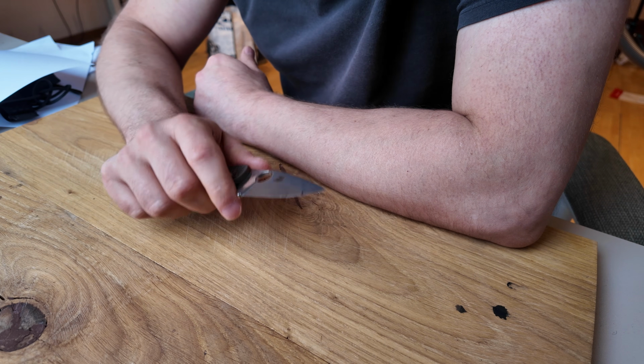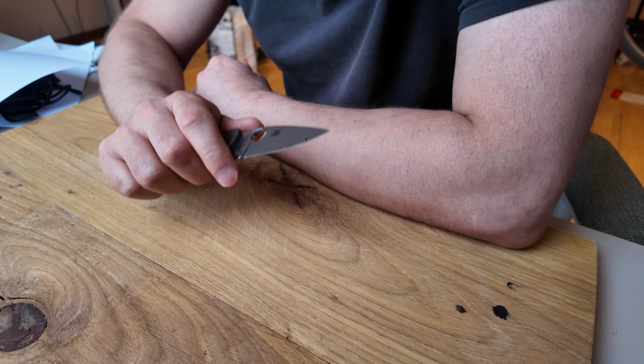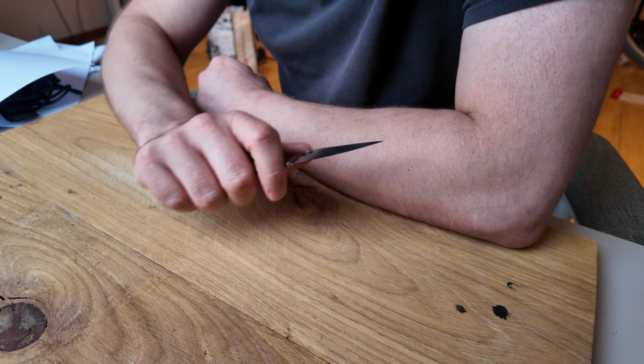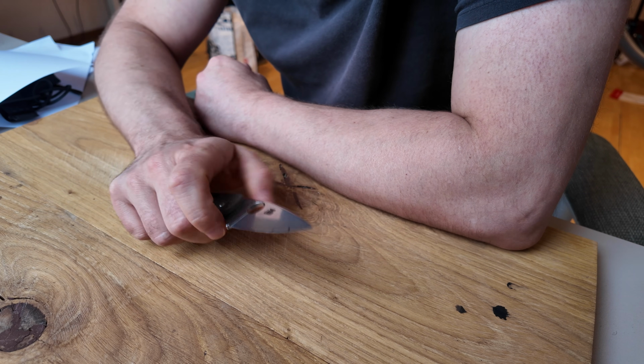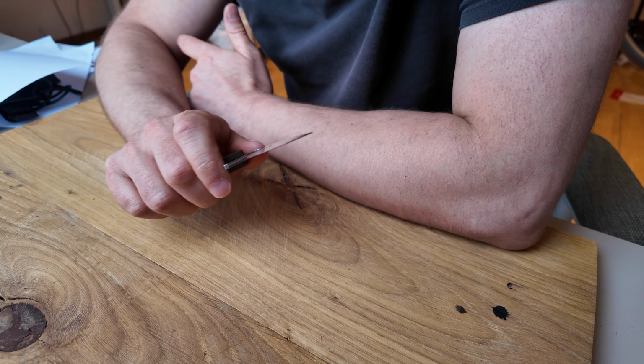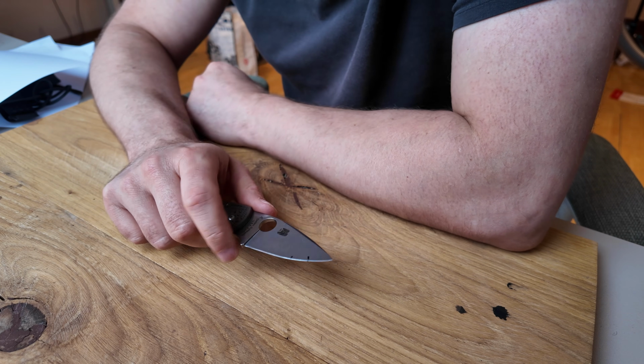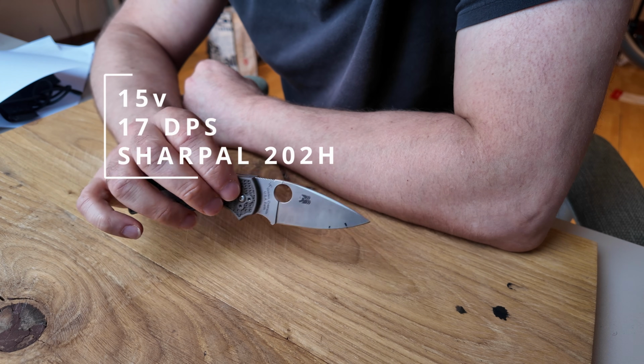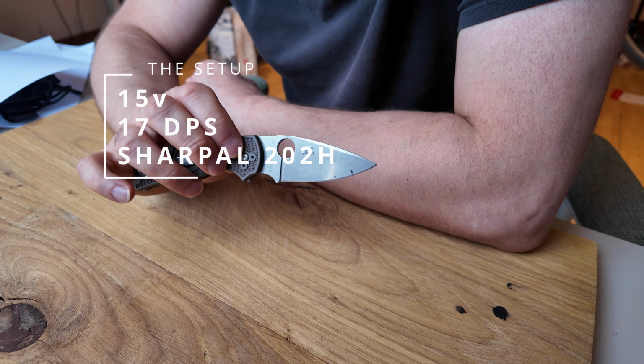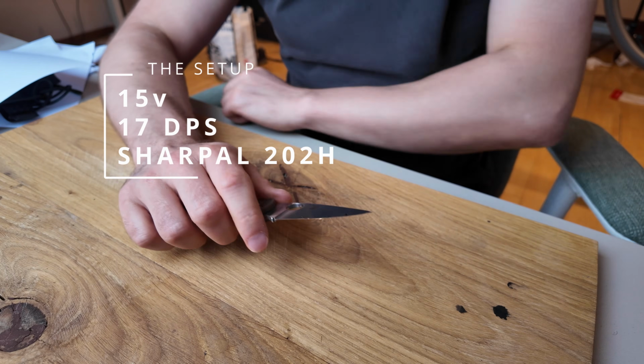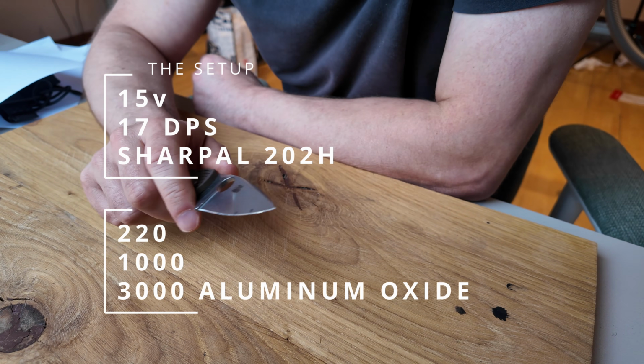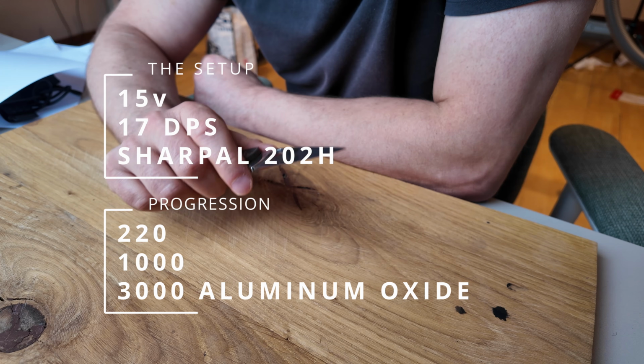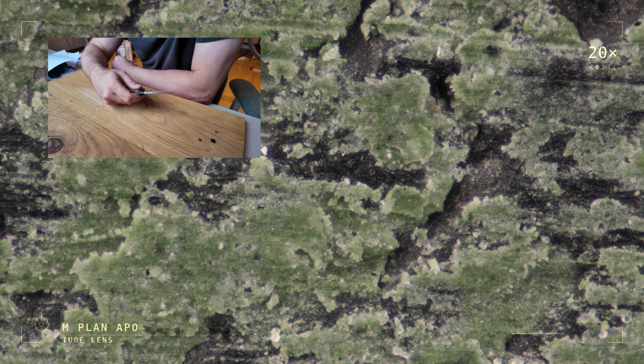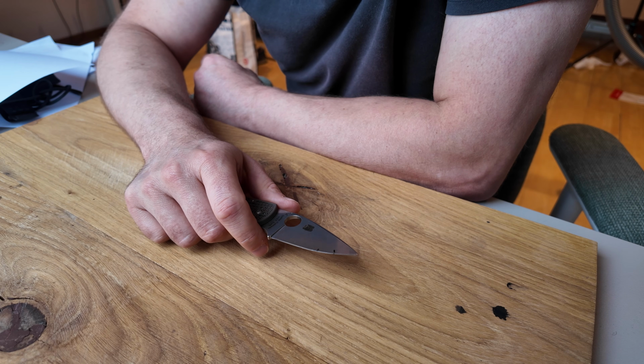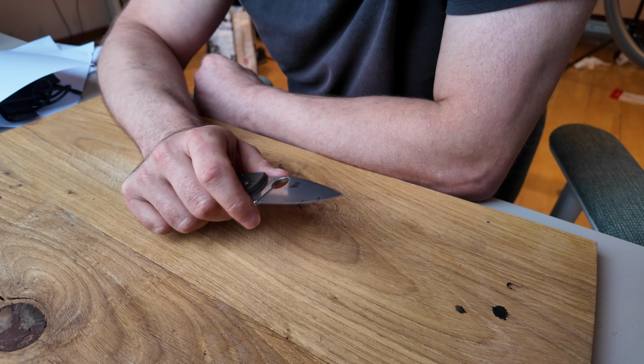Because we're testing apex stability, we need a test that focuses more on deformation than abrasion. Cardboard is mainly an abrasive test. Sisal rope is abrasive too, but it puts much more mechanical stress on the apex. I sharpened this Native 5 with 15V steel on a Sharpal 202H system with a 17 degrees per side. I finished with a 3000 grit aluminum oxide stone, and then I stropped it on 3 micron green compound, and then I did a cut test on 8mm sisal rope.